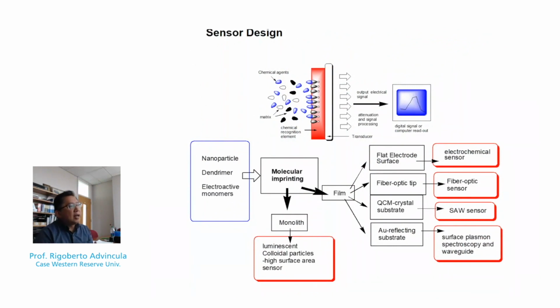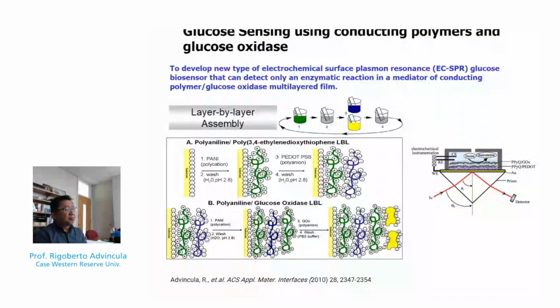Sensor means that we can have the surface plasmon resonance as a sensor for a sensing element that's deposited on the gold substrate surface. And then we can couple that with various chemistries or layer film configurations that make it sensitive. For example, we've reported 2 systems for glucose monitoring where we combine the glucose oxidase with the conducting polymer. We prepared it by layer-by-layer or electrodeposition methods.